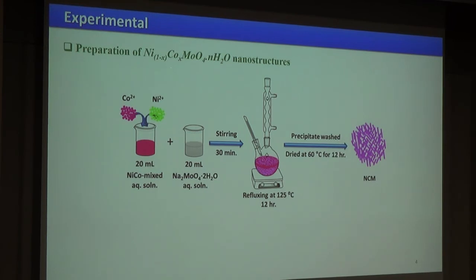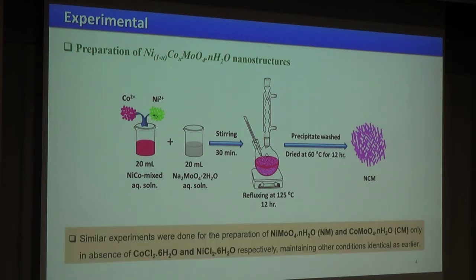Then that final mixture was refluxed in a preheated oil bath at 125 degrees centigrade for 12 hours. Then the final product precipitate was washed and dried, and we got our nickel cobalt molybdate, which is denoted as this. And similar control experiments were also done for comparison purposes, to prepare only nickel molybdate hydrate and also cobalt molybdate hydrate.